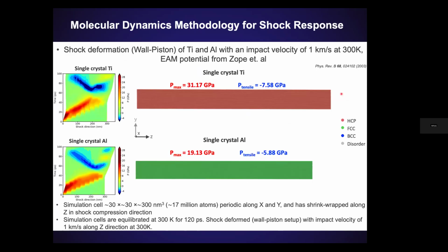Well, what about shock? We sort of understand what the interfaces are doing under uniaxial stress loading, but when I go to shock, would things be different? In this case, before we even started, we wanted to do some shock MD simulations on single crystal titanium and aluminum. We used the same potential, at room temperature. We impacted it at 1 kilometer per second. You have the position-time plots that I talked about, but here you're just looking at your target material. Basically you have a shock in your material that goes to the free surface, you get a release wave, and you're getting failure. This is single crystal titanium and single crystal aluminum. The shock goes from left to right, and release waves come in.